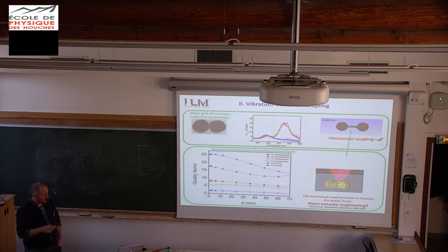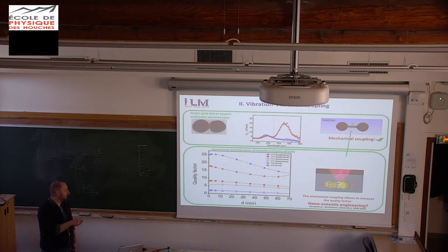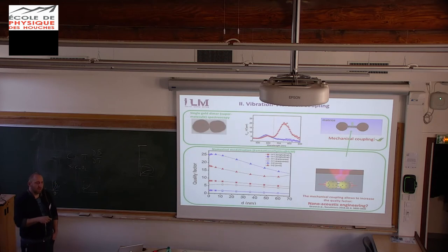Another interesting point, as I told you, is that we are measuring the width of the peak now, because we have a single object, so we have information on the damping of the system. These are also modelizations from Aurelien, and as you can see, when you reduce the distances between the nanoparticles, you increase the quality factor of your modes. So by controlling the distances between the nanoparticles, probably the matrix and everything, we are able to make nano-opto-acoustic engineering if we place the nanoparticles in a good position. So it's quite interesting.